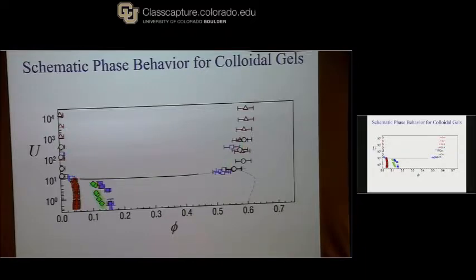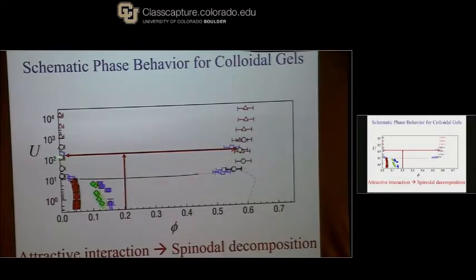It actually goes to pretty concentrated and pretty dilute. This is very, very low concentration. This is concentration right around the glass transition, right around the jamming transition. And so what's happening is that you come up here and you undergo spinodal decomposition. Here you have very, very few particles. Here you have a high enough concentration that you're just jamming them together.